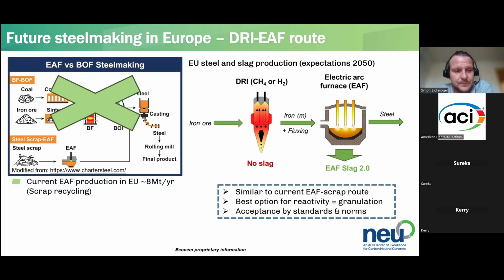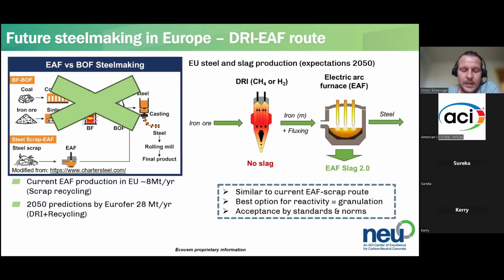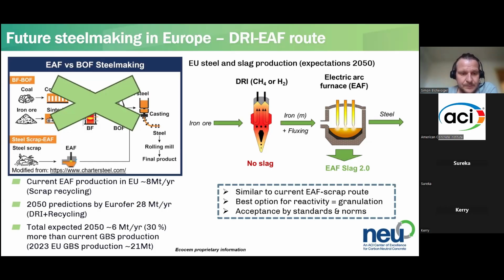In terms of volume, in Europe, we're talking about 8 megatons of scrap metal EAF slags per year at the moment. The prediction of Eurofer is about 28 megatons per year from DRI and recycling by 2050. So this would be quite a bit more, 30% more than current blast furnace slag production in Europe. So this is a huge material stream that needs to be valorized, because otherwise it needs to be stockpiled or used as aggregates. And it would be nice from a cement perspective that if we lose so much blast furnace slag, that we have a new material that we can use as a cement substitute.